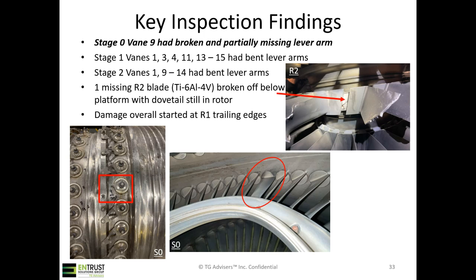Key inspection findings from our on-site evaluation. The stage 0 vane 9 had a broken and partially missing lever arm. So it's the middle and bottom left images. The bottom left one shows the missing linkage, and then the middle image shows the as found position of that vane.